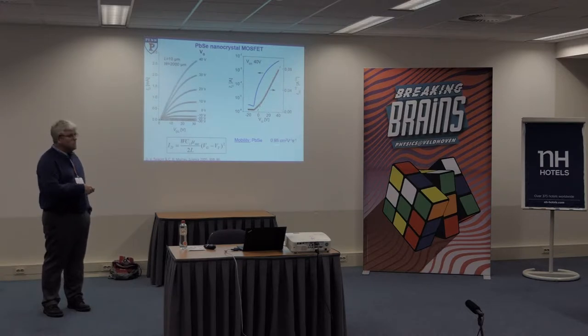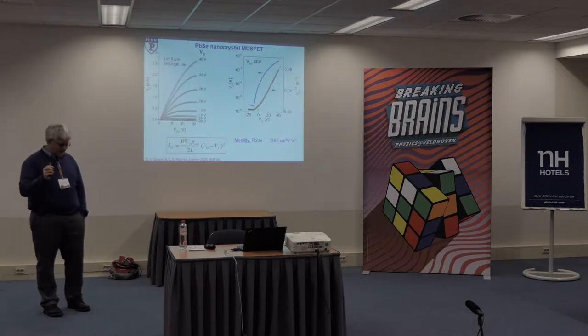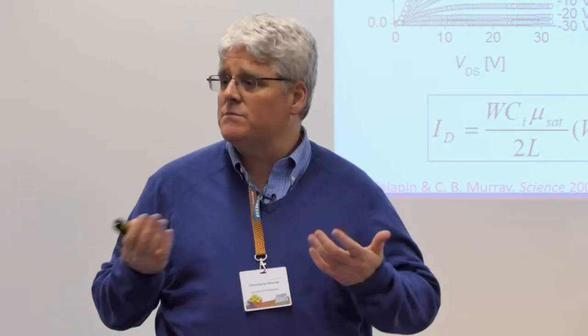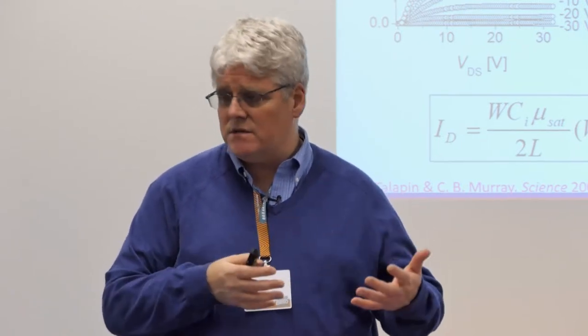ago, was around 1. And so that's just the edge where communities and physical models sort of overlap. So at mobilities below 1, people generally refer to hopping or site-to-site movement of charge in discrete steps, generally thermally activated steps, as being the most appropriate way to describe the electronic movement of charge in a material.